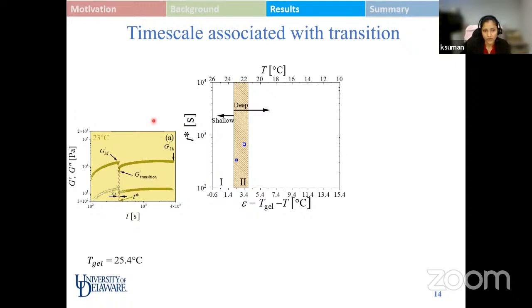This is the first region which we quantify in the center graph over here, where I plot the transition time as a function of extent of gelation, shown by the epsilon symbol. How do I characterize extent of gelation? It is basically the difference between the temperature at which I conduct the aging study at a deeper quench state, which is 23 degrees for this specific case, and T-gel, which is 25.4 as we characterized using the Winter criterion.